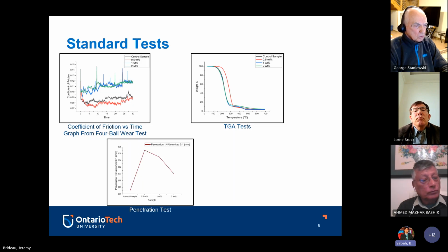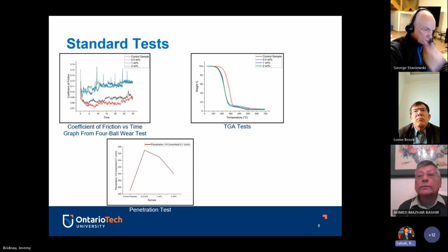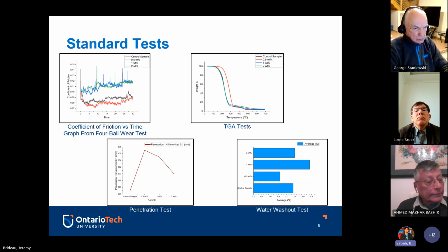Once we had that, we decided to go to Fluid Life and get a penetration test. This is basically just to see that adding the graphene doesn't change the NLGI grade. So we're dealing with a grade 2 grease, and we were able to maintain the same grade, which was extremely valuable. We were also able to do a water washout test, which showed that the 0.5 weight percent sample also had the highest percent retained when doing a water washout test.